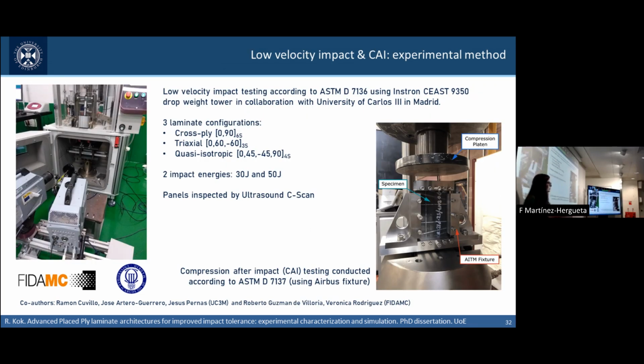The experiments were conducted at Carlos III University of Madrid, that has one of the biggest impact laboratories in Europe. It's also mainly sponsored by Airbus. We tested at 2 different impact energies of 30 and 50 joules of energy. And we also conducted compression after impact experiments in order to assess if there was any advantage of these technologies.